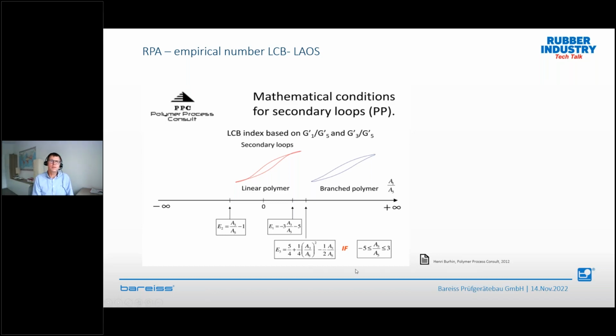And this means what we are using is the Fourier spectrum, the higher harmonics of our torque signal. And if these values are negative, we have a linear polymer. And if it gets more and more positive, it is a branched polymer. So this can be used also with control limits, so that with the supplier, or if you have a different supplier for the same polymer, you can double check if the branching behavior is the same, because branching is a very important parameter for the mixing line, for extrusion, for the viscoelastic properties. This is very important and this last test is very, very sensitive.